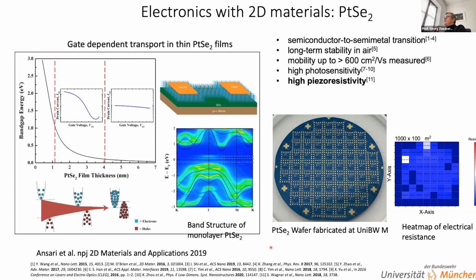However, with this method, we've never been able to really switch the material off, because we didn't really get monolayer growth in the channel region. Nevertheless, we've been able to make such wafers, where the best transistors we had were about on-off of several hundred, and mobilities of about 20. But it also showed that they had a good stability in air. Mobilities up to 600 have been reported by other people. They also have high photosensitivity and piezoresistivity.